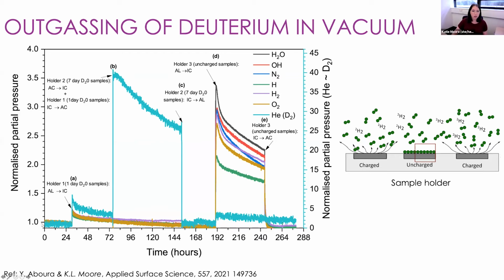At this point here, point B, Yasser introduced a sample that was charged with deuterium, a steel sample that was charged with deuterium, into that chamber. And you can see the deuterium signal in the vacuum chamber rises very dramatically. It starts to get pumped away, and then as soon as that sample is taken out of the chamber, our deuterium signal drops off dramatically. So what that tells us is that deuterium is outgassing from our samples in the NanoSIMS while we're trying to analyze it as well. So the key thing was to try and get the sample charged into the NanoSIMS, pumped and analyzed as quickly as possible before we lose too much deuterium from it.